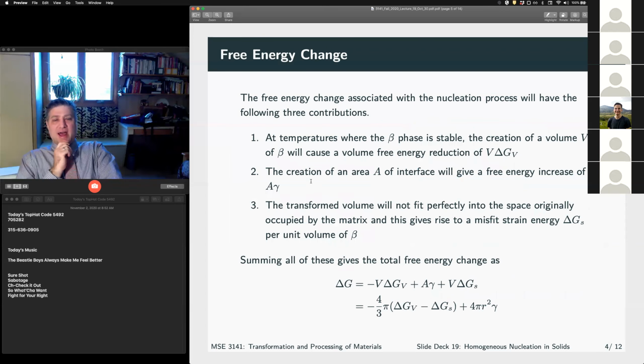So what does our activation barrier look like? Well, we have three contributions. We have our bulk Gibbs free energy. Our system does not want to be alpha. It wants to be alpha and beta, so we can reduce our overall free energy with the creation of beta, and that's our volume free energy term. That's reducing the energy of the system. The creation of our surface area is going to increase the free energy, back to our friend Gibbs-Thompson. And the transformed volume doesn't fit perfectly,